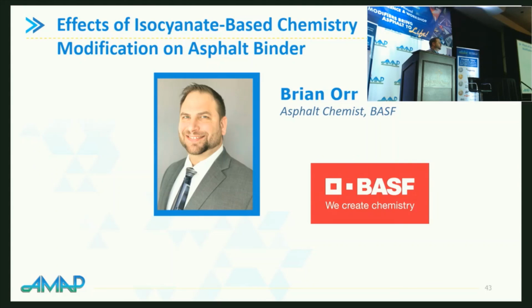Thanks, I see, yep, there we go. Brian, I'm wondering if you had any idea of what the reaction time is from the introduction of the isocyanate with the asphalt and complementing with the SBS. With asphalt and SBS at the same time, essentially, it depends on your loading. So a 1% modification can take an hour to 2 hours. Once you go up to 2%, it can take up to 6 hours. It just depends on, again, on that loading and, of course, your agitation.